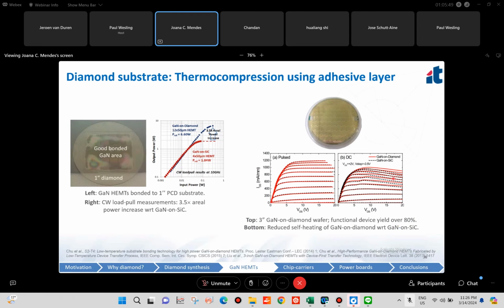And here on the right, you can see that the self-heating was actually reduced, because in a gallium nitride HEMT, self-heating manifests as a decrease in the drain current for increased VDS values. So we can see that GaN on diamond indeed shows less self-heating than GaN on silicon carbide.